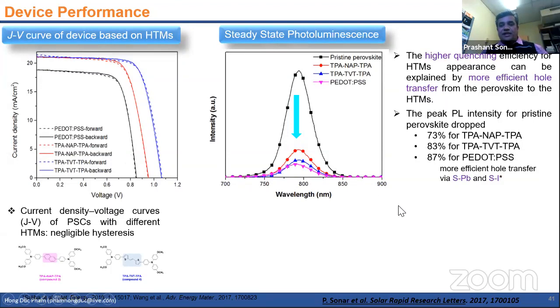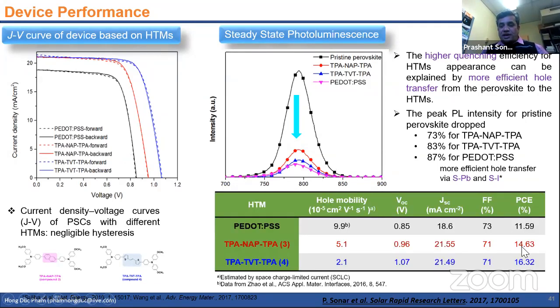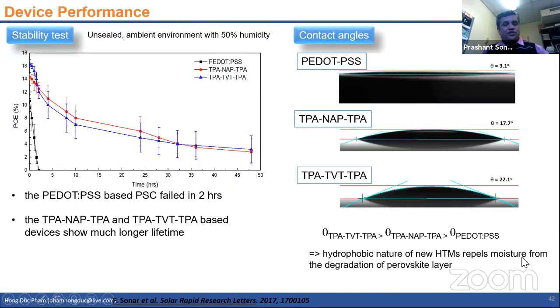So that clearly indicates that if the quenching is quite high, it means that there is some sort of good communication between our interfacial layers. And here is the comparison of these two molecules, and we got like 16.32%. We did also a stability study, although these were with that.